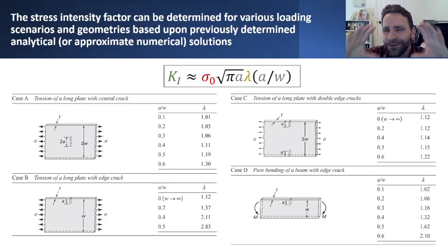As you get closer and closer to the crack tip, all those details further away from the crack tip start to become irrelevant. And the stress fields that appear due to whatever solution that you obtain will all start to look the same. So in this particular loading configuration and geometry, and in this configuration, and this one, and really any one that you could think of, as you zoom in your perspective really close to the crack tip, the stress fields will all basically look the same. And it's useful to look at solutions to problems that really try to examine what those stress fields look like really close to the crack, which have really general applicability to any of these different loading and geometry